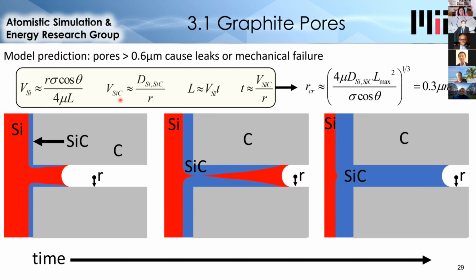The second equation is the velocity of the silicon carbide layer. And so this is basically the reaction rate, the main resistor of which is the diffusion of silicon or carbon through the silicon carbide layer. And so it's represented by this scale, the diffusion coefficient divided by the thickness, which is the radius of the pipe approximately. Now, combining these equations, I can estimate the critical radius if I choose a maximum length that we would tolerate silicon leaking.